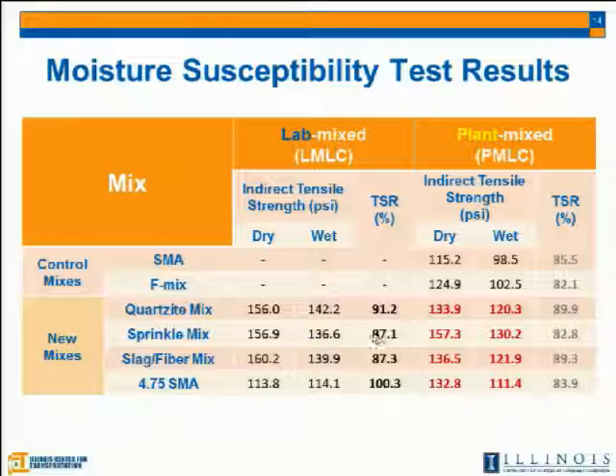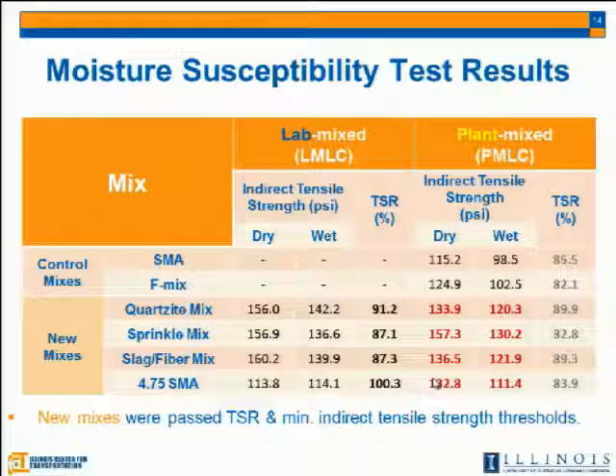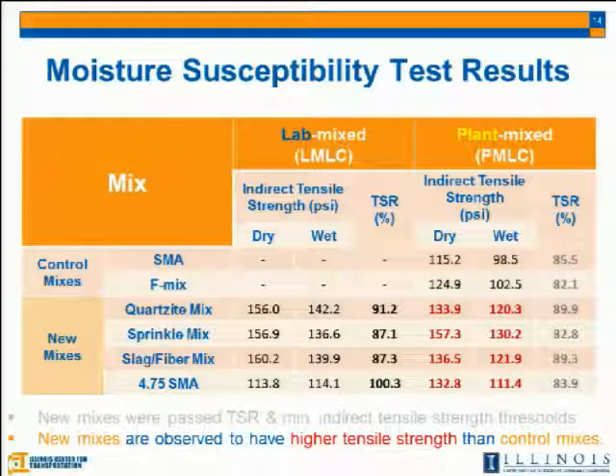The Illinois TSR threshold is that we should have 85% of the TSR value and then 60 psi minimum strength. So all of our mixtures meet both thresholds. And to compare with the control mixture, new mixtures, we can see this column actually. So new mixtures will pass the TSR. Yeah, new mixtures are observed to have the higher tensile strength than the control mixture.